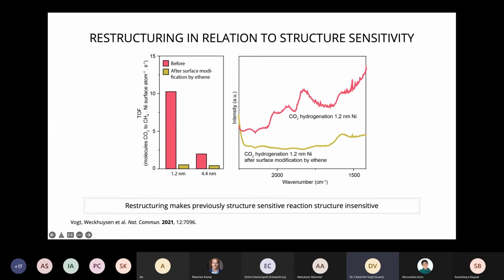Before, we see a clear difference in the turnover frequency, and after, this structure sensitive reaction, because of that restructuring due to the ethene, is now structure insensitive. It is still active. We did still see CO peaks adsorbed onto the surface, but those were very specific CO peaks that we saw. So it does indicate indeed that there was only a certain type of site that was still exposed.